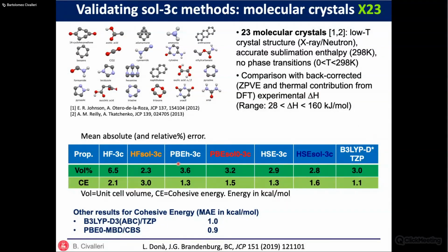So here I report the results for the original 3C method and the new SOL3C method. You can see the mean absolute error, or the relative percentage error, on the volume, also with respect to triple zeta quality calculations at the B3LYP level of theory, and the cohesive energy. And you see that the errors are really consistent within the methods. So we didn't see any degradation of the results with respect to the original.